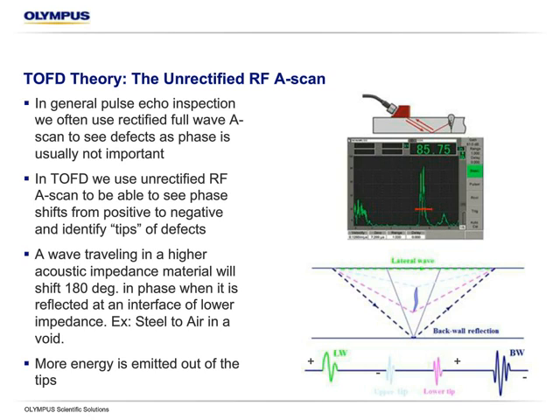That's because of the interface between the steel, or whatever the material is, and the air which is surrounding it at the back wall interface. So these tips are really what we're looking for when we're going to do precise sizing. It's really the foundation of how we use time to measure with time of flight diffraction.